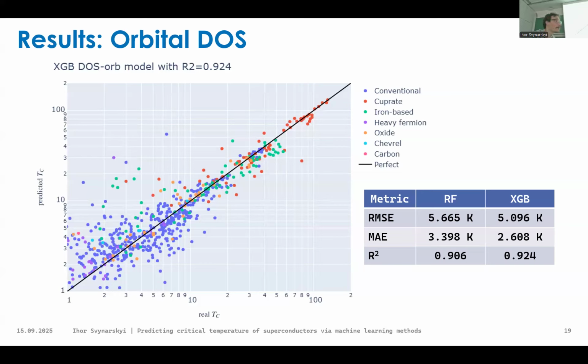distributed. Basically, cuprates mostly have temperatures between like 50 kelvins and 150 kelvins, so it's on the same order of magnitude, while conventional ones go from slightly lower than 1 Kelvin, like 0.5, up to 10 kelvins, even more. And in the case of the iron-based, it's 40 kelvins almost. So it's like a 2 orders of magnitude distribution, so they are broader distributed.